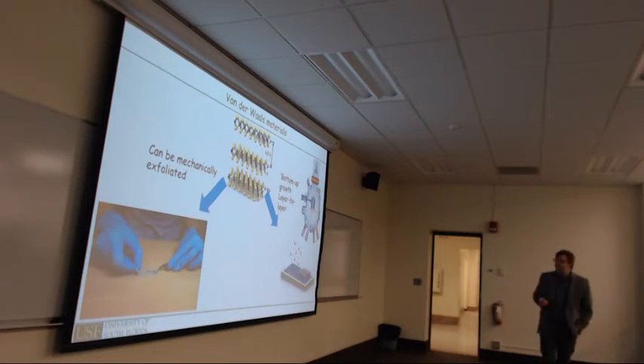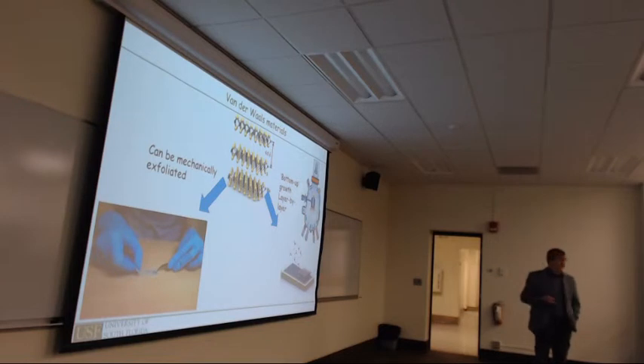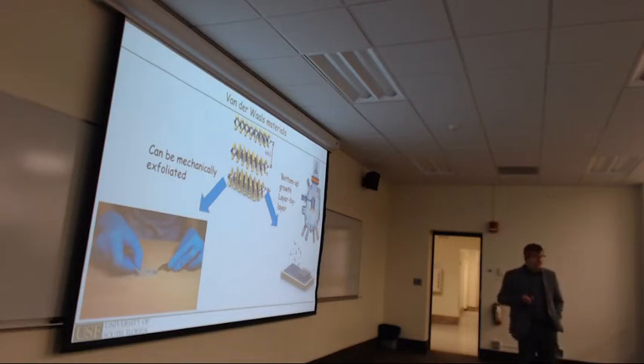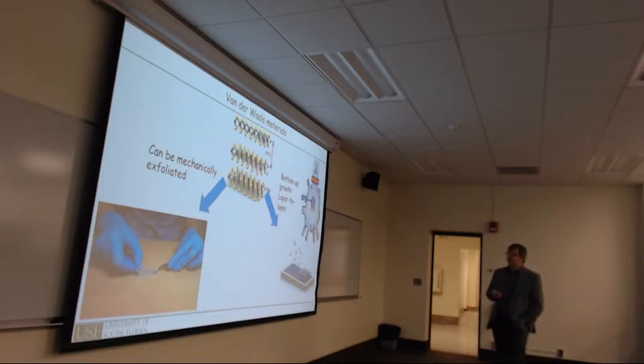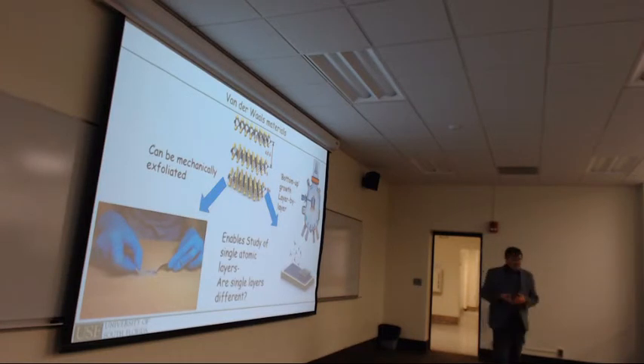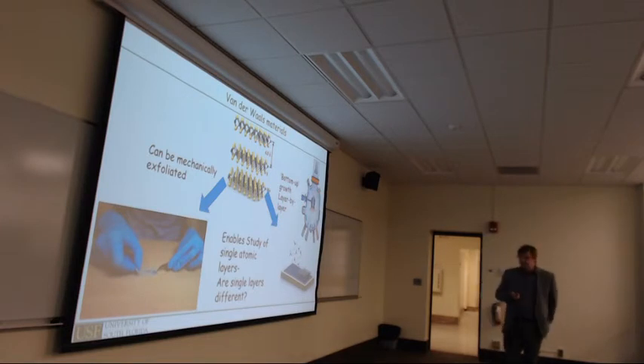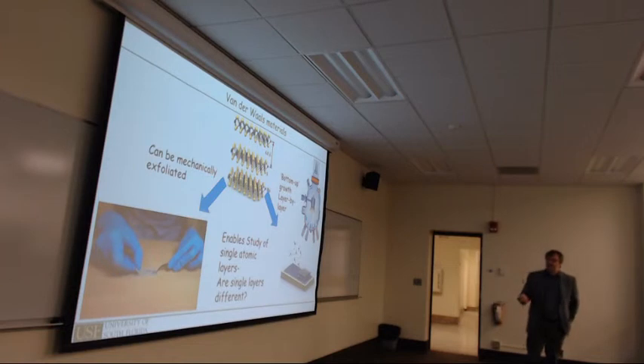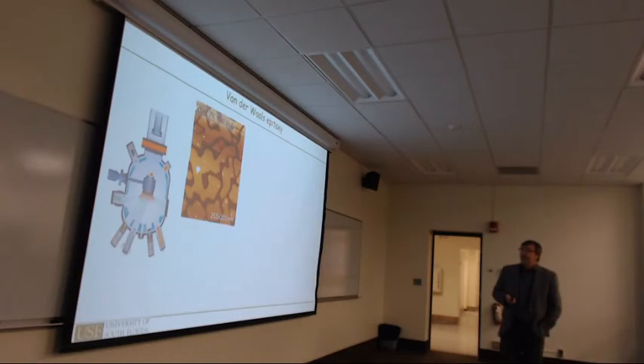and the method for growth I'm using is molecular beam epitaxy, where you have different sources with different components. So for example, for molybdenum sulfide, you would use a molybdenum source that evaporates molybdenum, and a sulfur source. Also, in my work, I'm mainly growing selenides, so you would use a selenium source. Both ways essentially allow you to grow single layers of these materials and study their properties. One question would be, how are single layers different from bulk materials, or are they just the same properties as bulk materials, since they only interact via weak van der Waals interactions? Right.